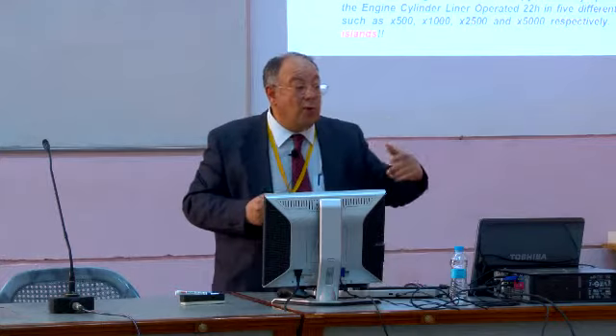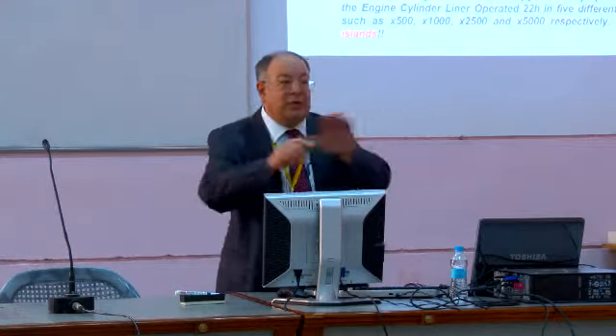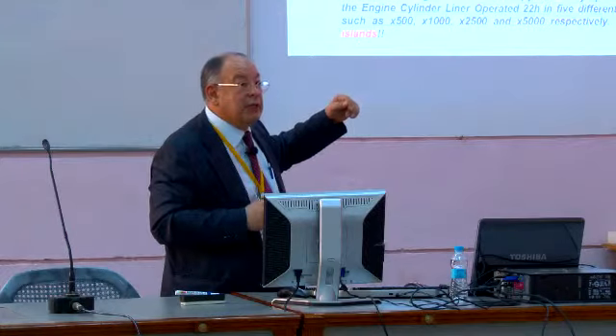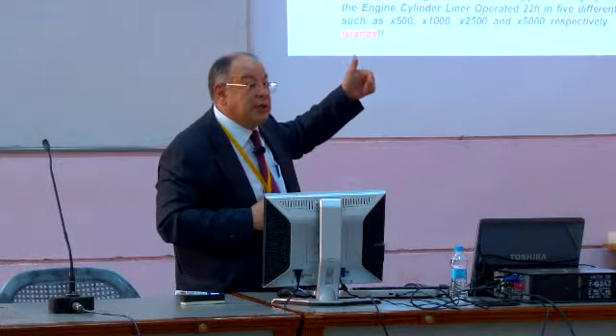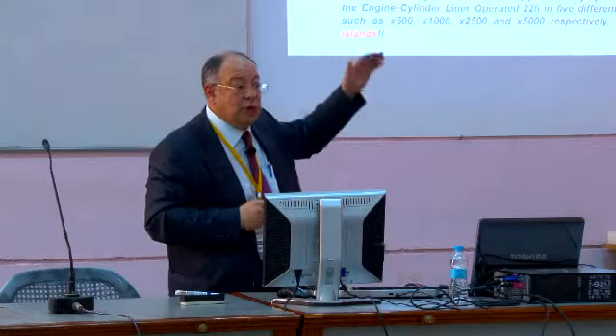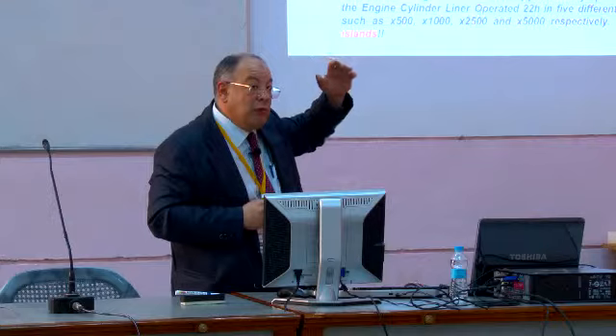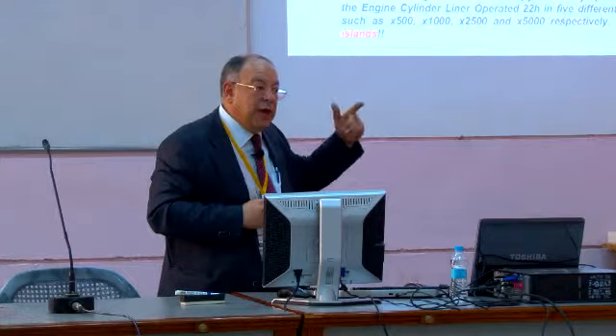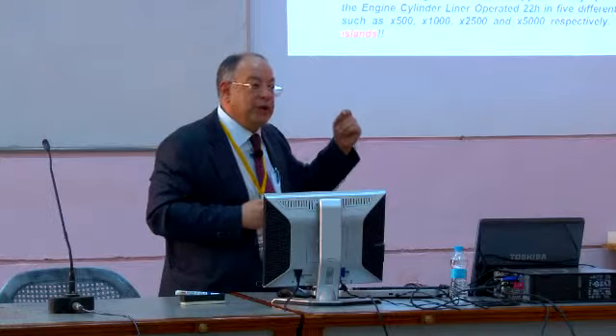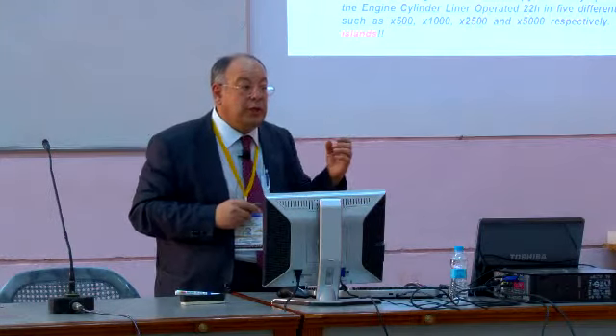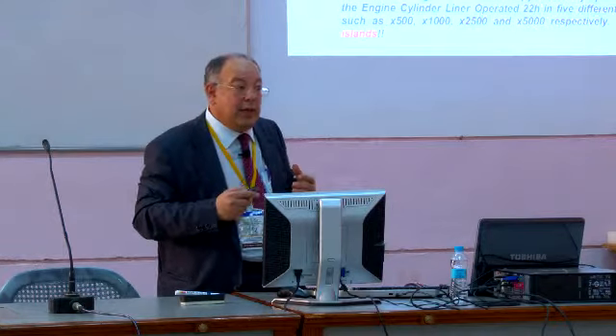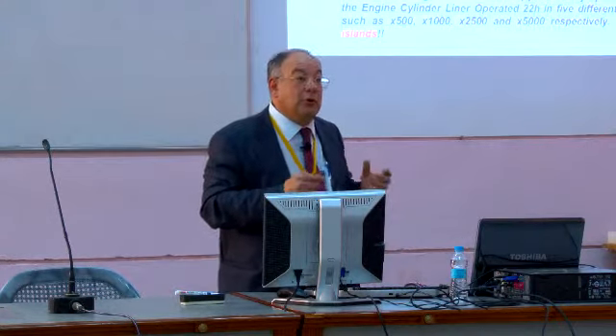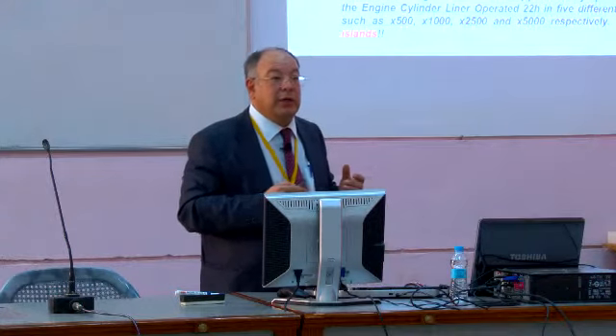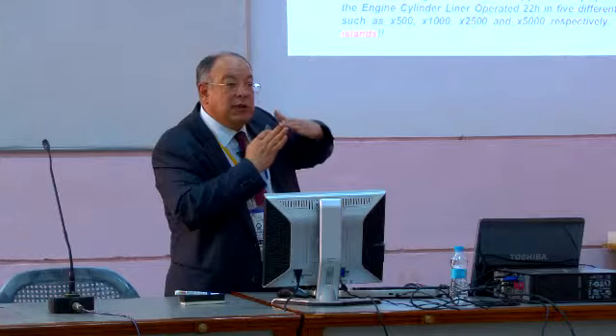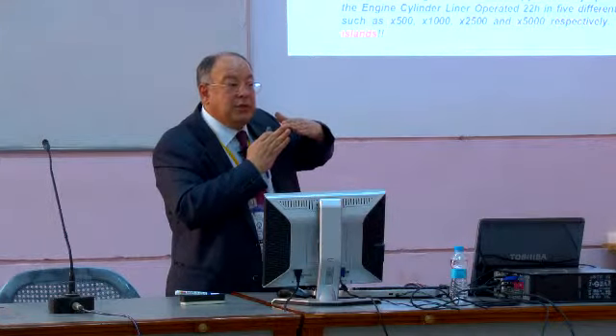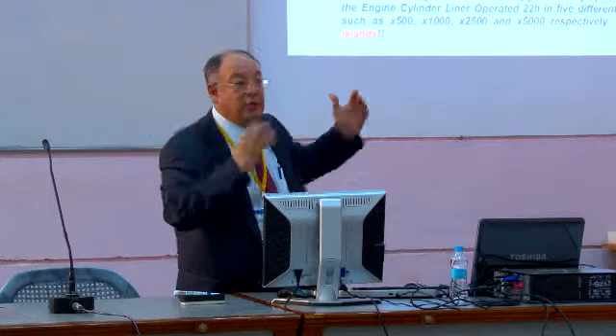What happens for additive layers? The additive layers form as islands on the surface, not everywhere - they don't cover it fully. Mostly we found those layers at top dead center, because top dead center is the worst condition under boundary lubrication, with high load and maybe high temperature. But because of the good compression, there is no leakage, no blow-by, and the additives really play a good role to protect the surface. Even that protection is very small - when it is sliding there is no blow-by, nothing, no leakage, except if